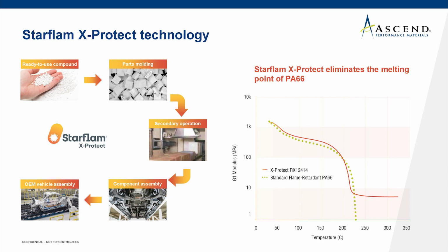The formulated polymer with X-Protect technology and gone through that secondary operation follows the red solid line. We start at a very similar level and we see the same physical effects of a regular PA66. So some softening throughout the glass transition temperature, a loss of rigidity as we approach the melting point. But then at a certain temperature level, we maintain a storage modulus of around 7 to 8 megapascal, even clearly past the melting point. Now, this is how far we can take it with the DMA method.